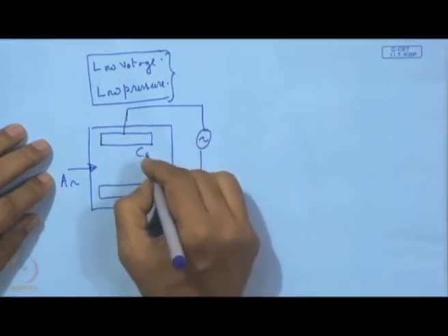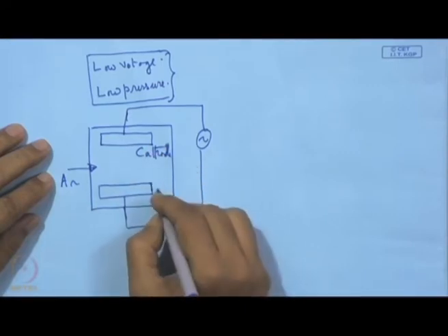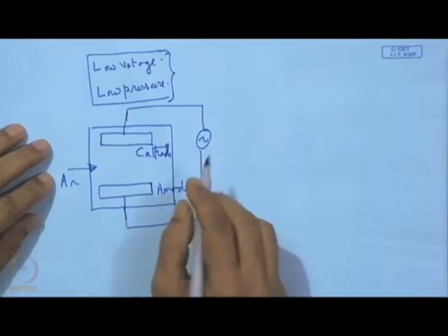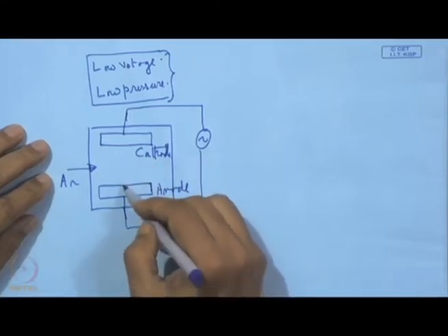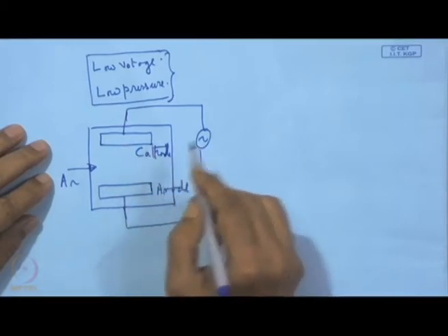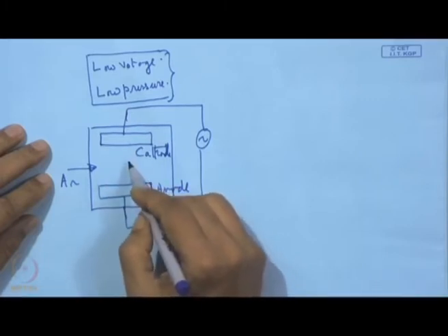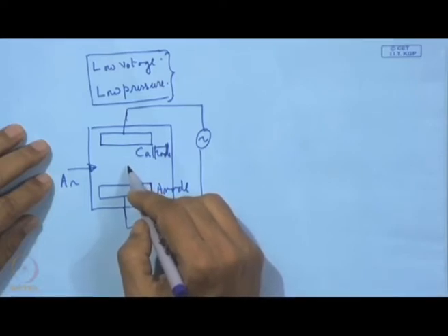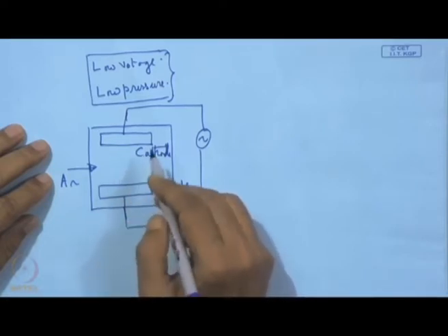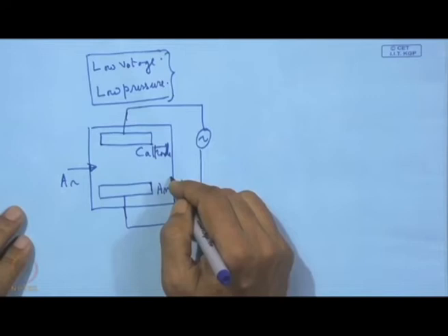So, this is cathode and one anode plate, or the wall may also be anode, but what is important here is that the secondary electrons that would emerge from the cathode had it been DC would be pulled into this plasma volume where they become primary electrons, and with collision or even without any collision they can strike the anode surface and get lost.